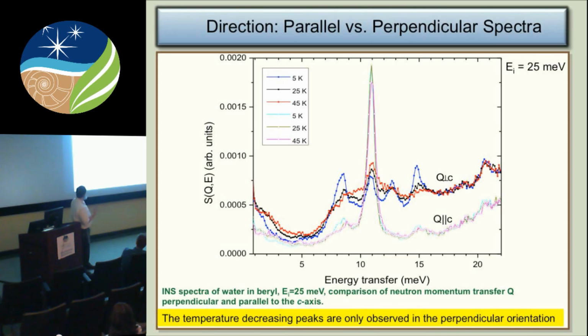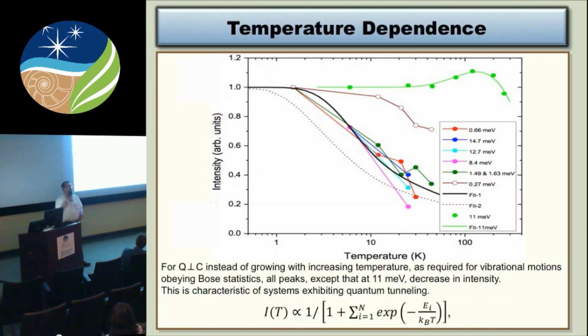Again, if we look parallel and perpendicular to C, you can see that most of what we're seeing here is in the Q perpendicular direction. So whatever is happening is happening here. It's happening around the channels, not along it. Okay, again, you can see this decrease with temperature.